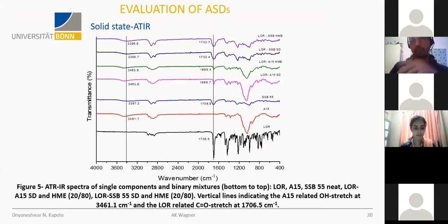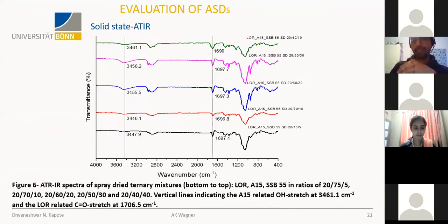While in the case of the amorphous solid dispersion, loratadine and Affinisol in spray drying and hot melt extruded, we observed the C=O group was decreased to 1699, and the OH group was at 3461. While in the case of shellac, it was not that pronounced, indicating that there is less interaction. In the spray dried formulation for the ternary mixtures, in the case of 20-75-5, the OH stretch was decreased to 3447, while in the case of 20-70-10, it was decreased to 3446 compared with the API and polymer mixture, indicating a higher level of interaction.